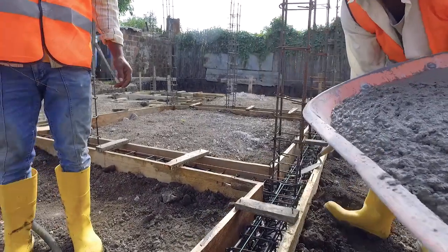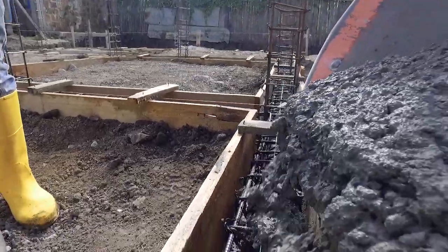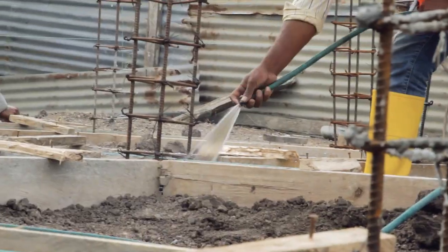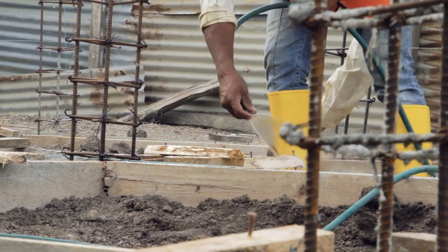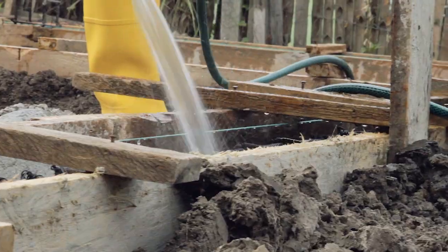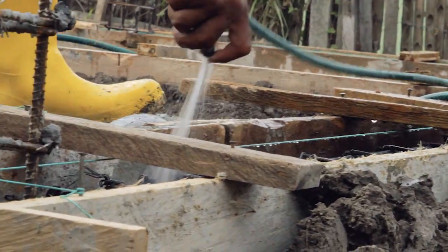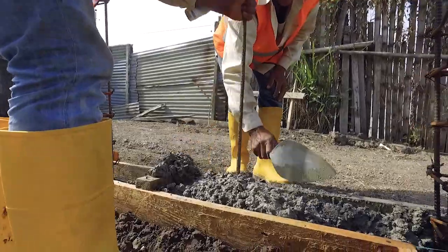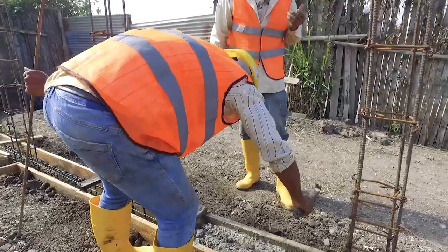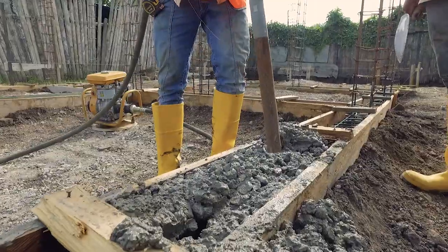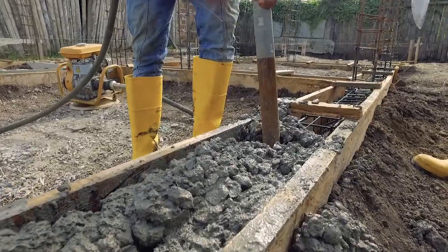Pouring of concrete in the plinth beam. For a correct pouring of the concrete, the following steps must be followed. Before pouring the concrete, the formworks must be wet, otherwise the wood from the formwork could absorb the water from the concrete mix. Compact the concrete using a rebar and a hammer, or better, with a needle vibrator.